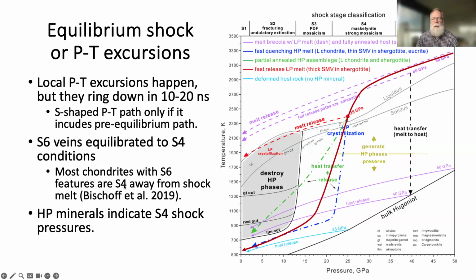He had a student look at, I think, like 1,000 different samples and shock classify just hundreds of samples. And what they found is that even in the most highly shocked samples, when you get away from the melt vein, the shock stage is S4, even in Tenham.